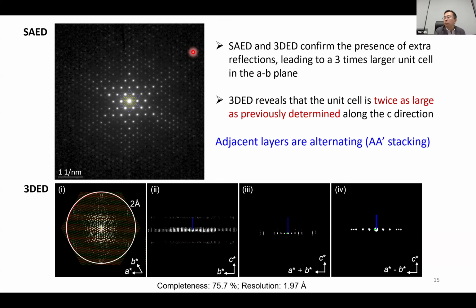Okay. Yeah, but I think you're asking about the real space averaging of multiple unit cells to enhance the signal to noise. But we are very cautious to do that for local non-periodic structure, because in principle you can only do the real space averaging for periodic structures, right? So we have done that once for surface termination structure. We assume that all the surface terminations adopt the same termination mode, and then we do that. But for the grain boundaries, we don't think it's appropriate to do the real space averaging.